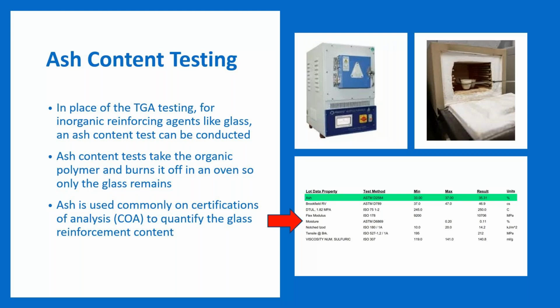And so if it's glass filled, you're generally going to see ash, which is what I've highlighted in the little snip of a cert that we get for some of our filled nylon. You can see that this is a 33 to 37, so nominally a 35% glass filled grade. This particular lot of material that was sent to us and we sold to our customers came in at 35.31% glass. And so a quicker, not as complex or complicated way of doing it would be to do an ash content test for glass. So that's done pretty frequently as well.